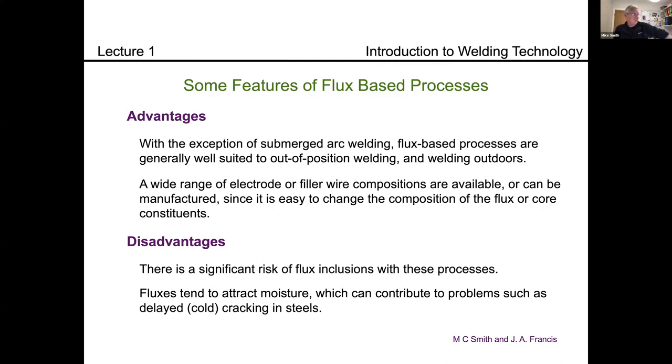So very often when you're doing a flux-based welding process, you have to make sure that all your electrodes or your flux are baked in an oven to dry them before they're used. And clearly, if you're welding up a ladder in the rain, that might be quite difficult. So there are potential issues with them.